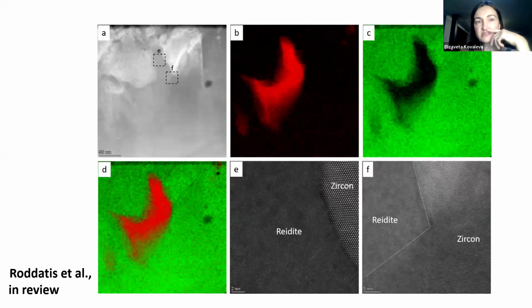In A, you don't see anything. But in B, C, and D, this is spectral imaging, and you can see the red is reidite and green is zircon, and this kind of half moon shape, I don't know what kind of shape it is, enclosed in green zircon. And in E and F, that's an enlarged high resolution TEM image, and you can see crystal lattices of zircon and reidite, which are very different from each other. So you can really see its different phases with quite a sharp contact with each other.